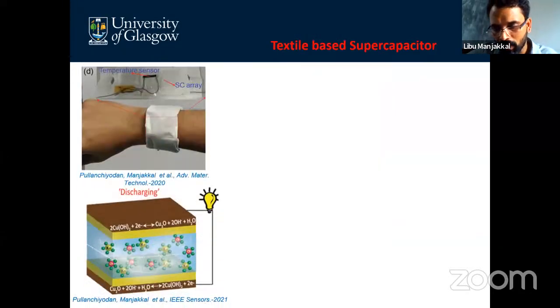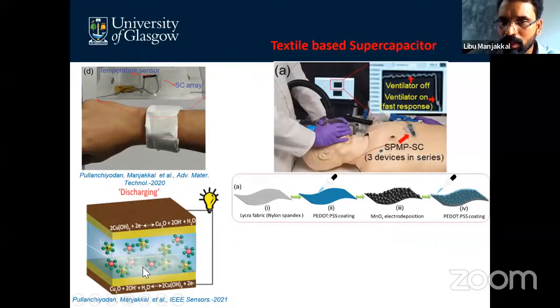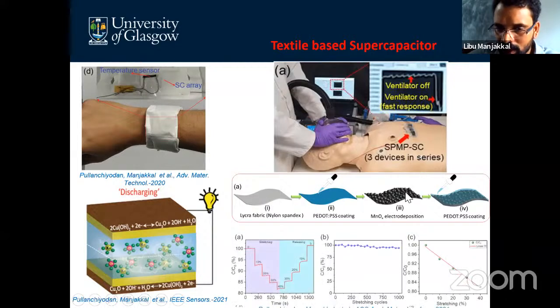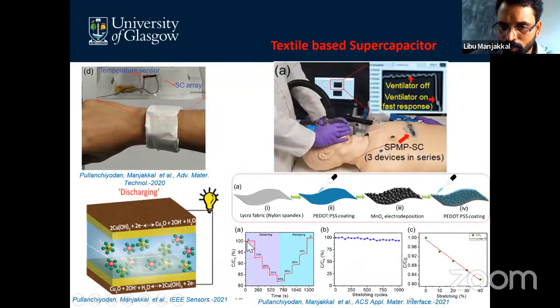In addition to that, I also participated in another work with my colleague. We developed a metal coated textile as a substrate, and then fabricated a supercapacitor to power a temperature sensor. And in another application, we found that the flexible or stretchable textile based supercapacitor itself acts as a sensor. For this, we fabricated a supercapacitor on a stretchable substrate, and then studied different stretching and releasing cycles from 0 to 40%, and we found that depending on the stretching, there is a change in the capacitance value. That means the stretchable supercapacitor itself plays a dual function role. It acts as an energy storage device along with being a sensor.